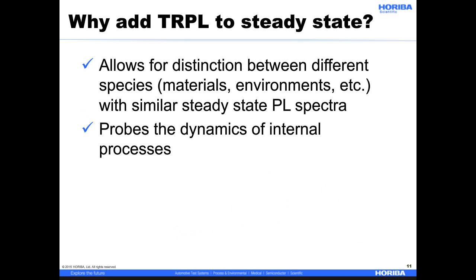While steady-state PL can provide a large amount of information, time-resolved PL provides additional complementary information on the system under study. For example, if there are two species with identical steady-state PL signatures, they may be distinguished by measuring their lifetimes. This could be the same material in different environments, for example, at the interface or in the bulk material, or different materials altogether. TRPL also provides a probe into the dynamic processes in the system.